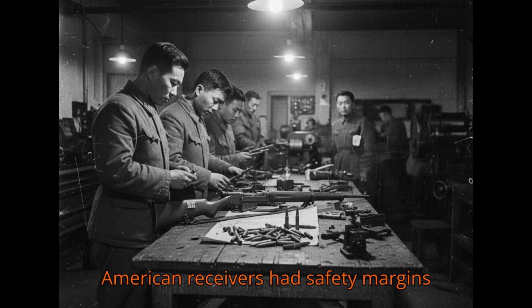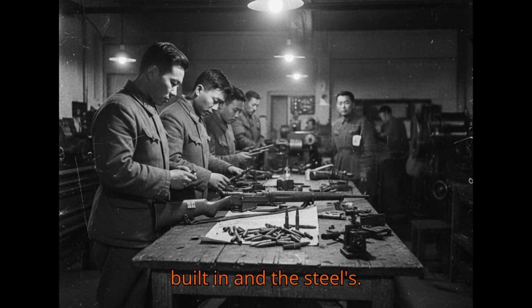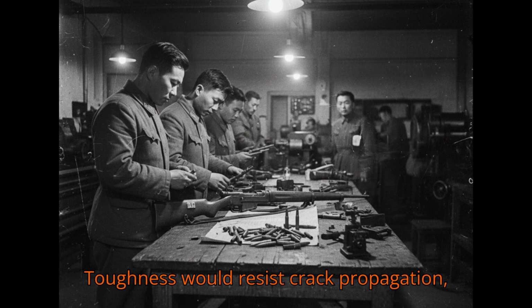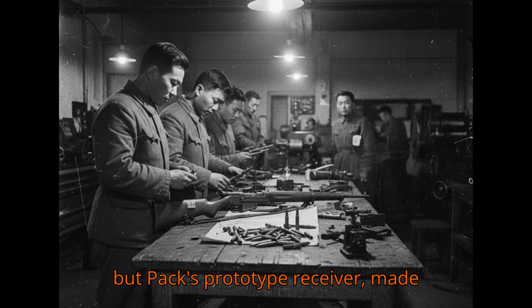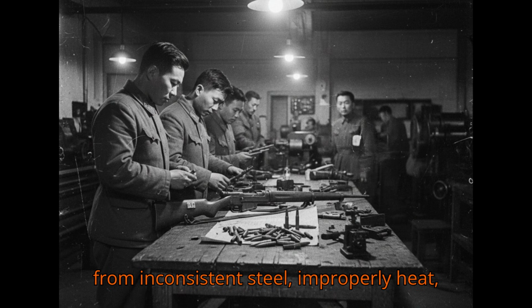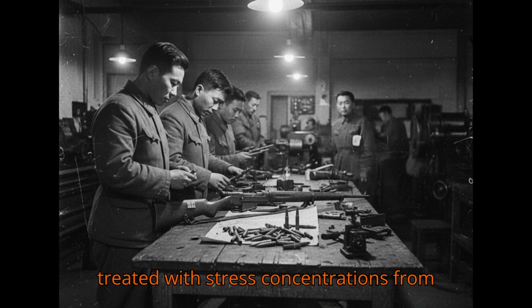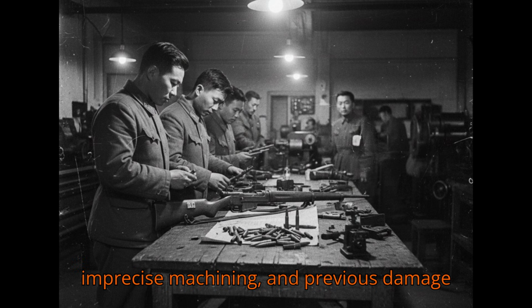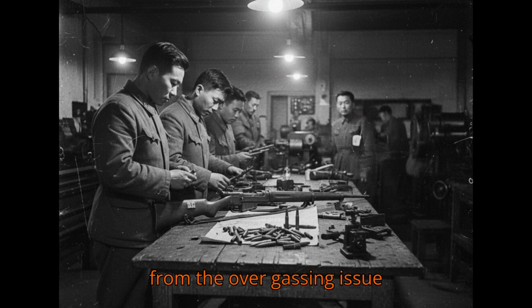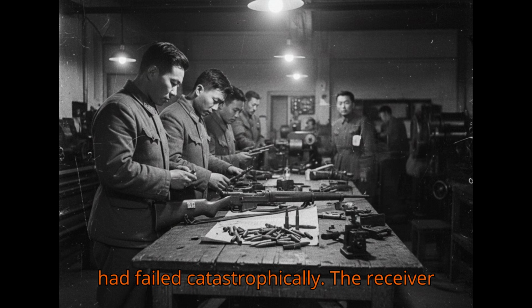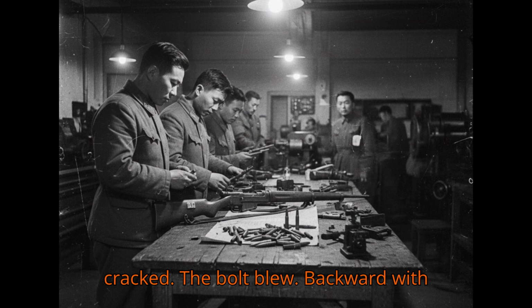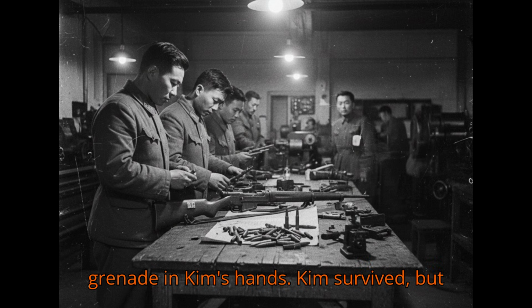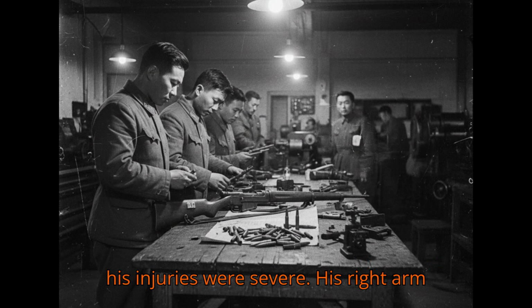The American receivers had safety margins built in, and the steel's toughness would resist crack propagation. But Pak's prototype receiver, made from inconsistent steel, improperly heat-treated, with stress concentrations from imprecise machining and previous damage from the overgassing issue, had failed catastrophically. The receiver cracked, the bolt blew backward with nothing to contain it, and the rifle essentially turned into a fragmentation grenade in Kim's hands. Kim survived, but his injuries were severe.